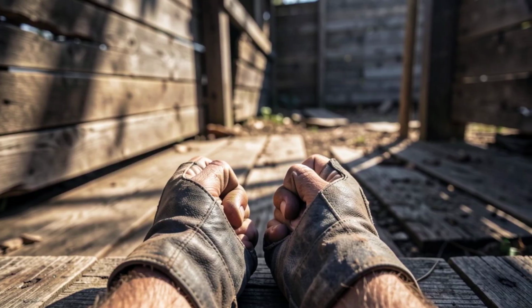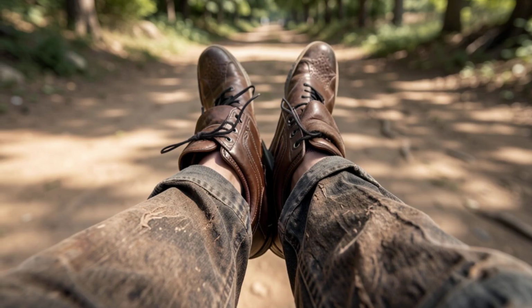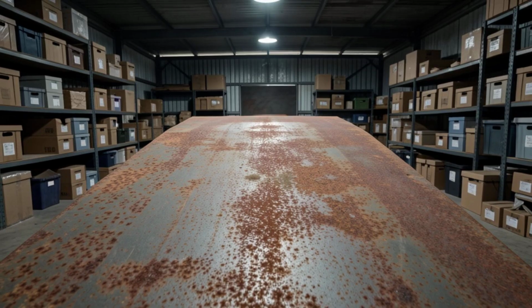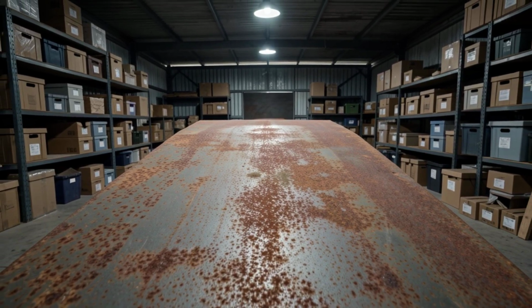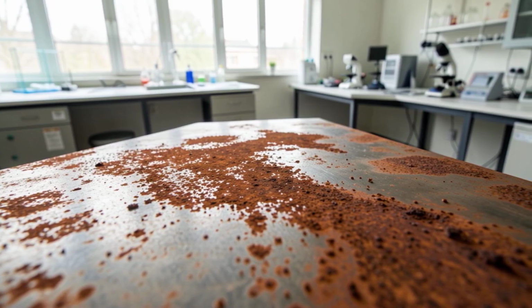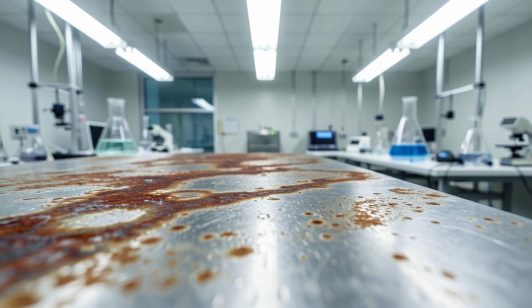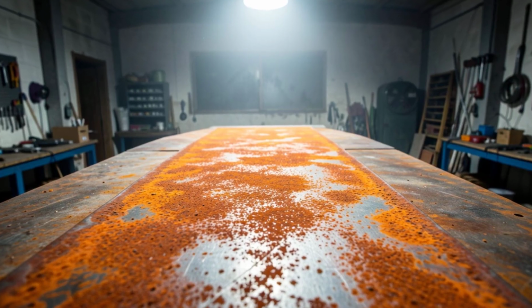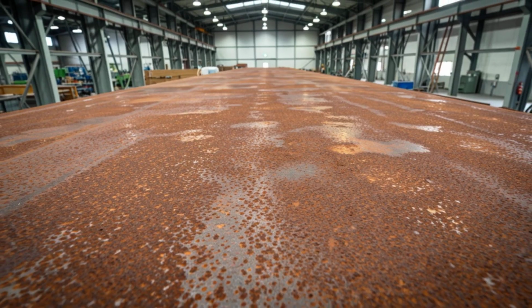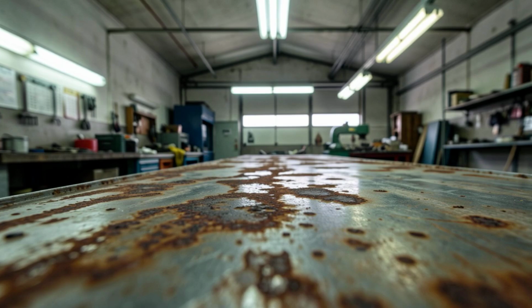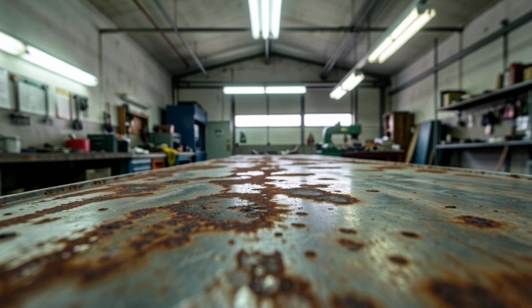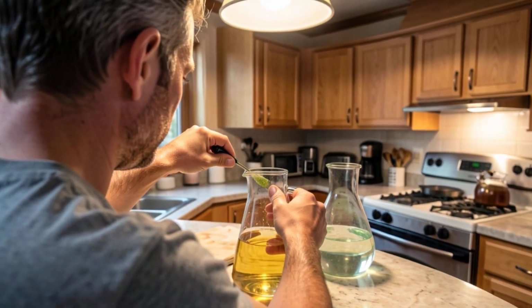If you leave those acid traces on bare, clean metal and expose them to air, you will trigger what metallurgists call flash rust. Flash rust is not the slow, gradual rust you are used to seeing develop over weeks or months. It is an extremely rapid oxidation reaction that can coat an entire clean metal surface in a uniform layer of bright orange iron oxide in under 20 minutes at room temperature. You will go from clean, shiny metal to fully orange metal faster than it takes to find your next tool.